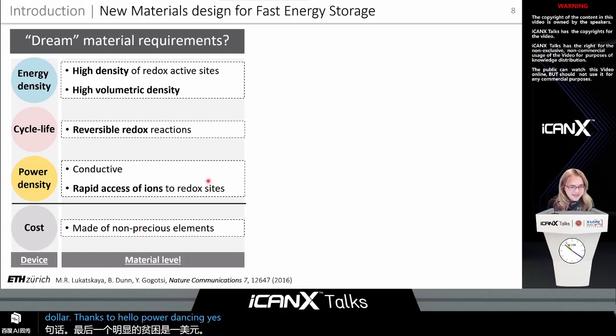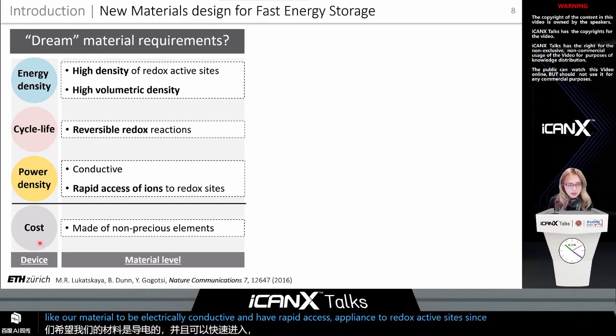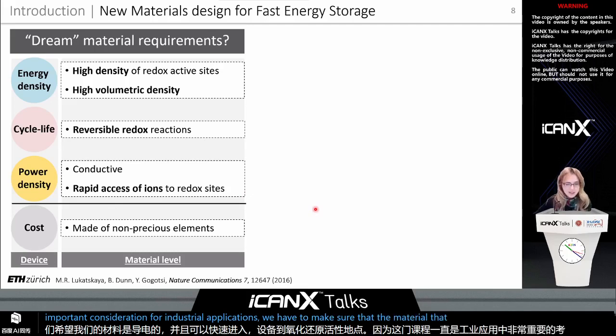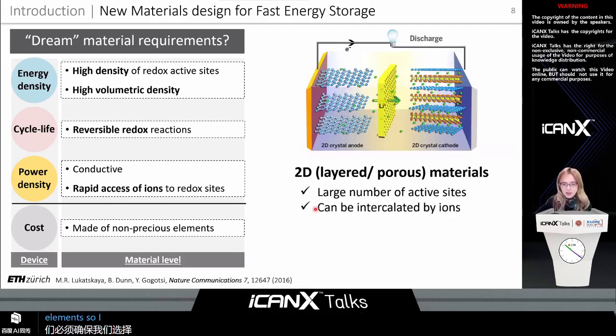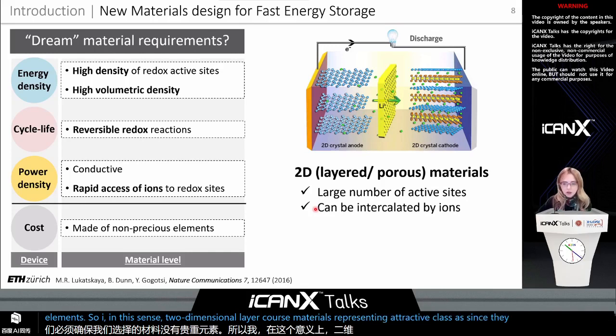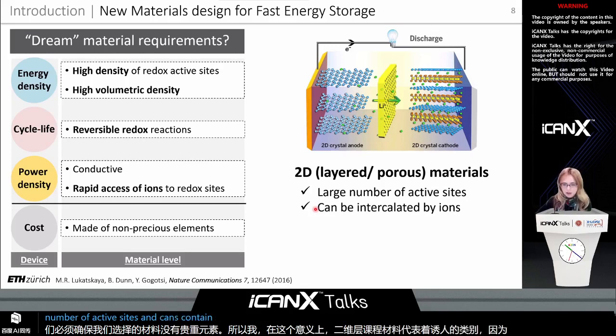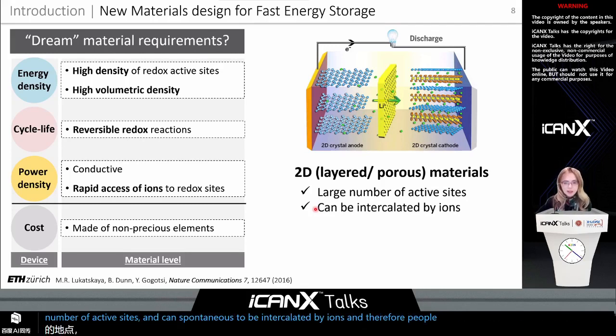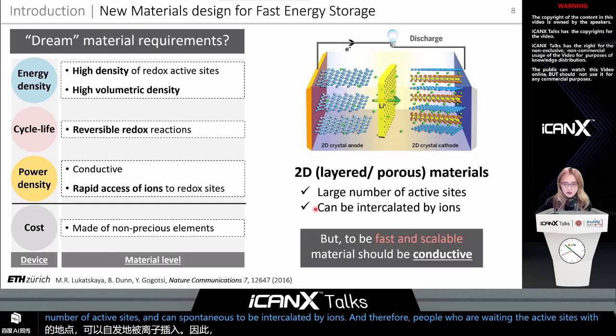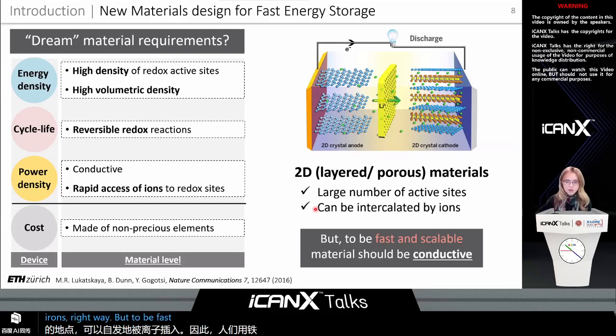Yes. Okay, excellent. Since we want to maintain high power density, we would like our material to be electrically conductive and have rapid access of ions to redox-active sites. Then, since cost is always a very important consideration for industrial applications, we have to make sure that the material we select doesn't feature precious elements. In this sense, two-dimensional layered porous materials represent an attractive class, since they feature a large number of active sites and can spontaneously be intercalated by ions, thereby prepopulating the active sites with ions right away. But to be fast and scalable, the material itself should possess sufficient electrical conductivity.